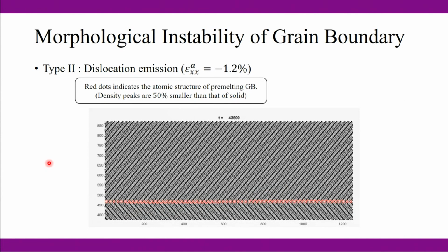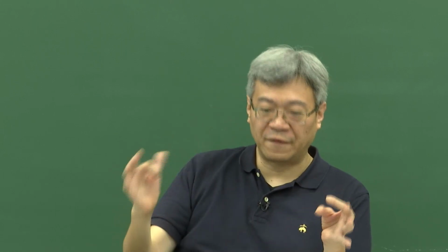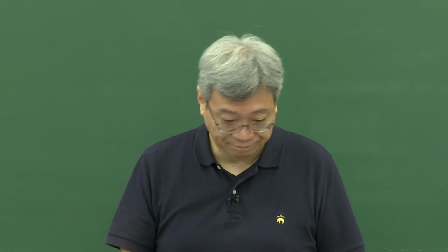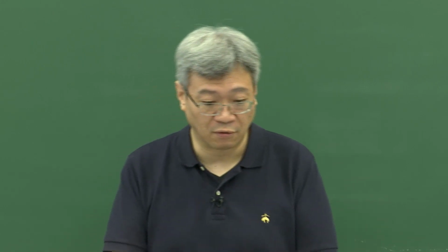But the thing is that what is happening here, I mean, in classical theory, we don't expect to see the grain or the surface between an identical solid, right? In that case, even if there's a compression, we are not expecting to see the surface undulating, because by doing so, for a wavy profile, you are not gaining any reduction in the elastic energy or things like that, right?